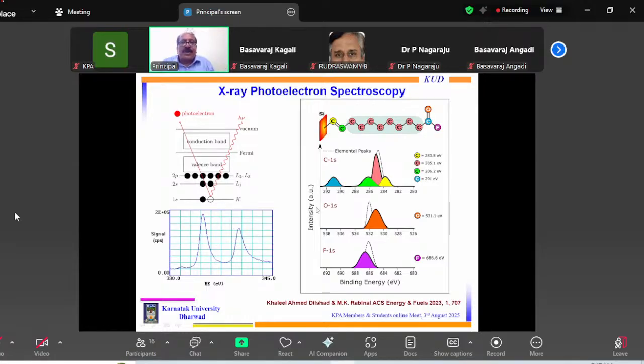So now if you record this XPS spectrum of the carbon, what you see is, suppose carbon in a free condition, you're supposed to get a dotted line, and this carbon, which is sitting in a highly strained environment, has a higher binding energy. Therefore, it appears here. And this carbon will appear here, and this will appear here. Therefore, by a shift in the position of the binding energy, one can precisely tell how it is sitting and what kind of chemical bonding it is establishing with respect to a given substrate.